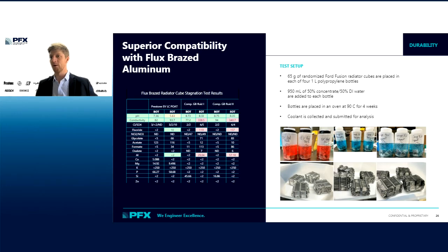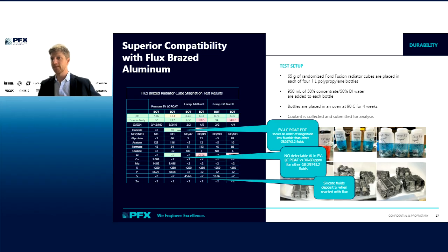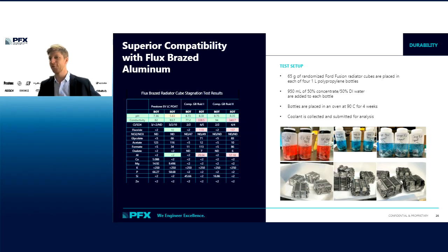The one thing to note, electrical conductivity, end of test increase for the Prestone fluid, we're still under 100 microsiemens. For the competitive fluids, they start at 77 and 94 microsiemens respectively, and their end of test value is over 300. So significant increase for those fluids. Fluoride levels is another important one to call out. You'll see that the Prestone fluid picks up around 10 ppm of fluoride, and I've just covered it up there. The other 2 fluids pick up 120 and 160 ppm.